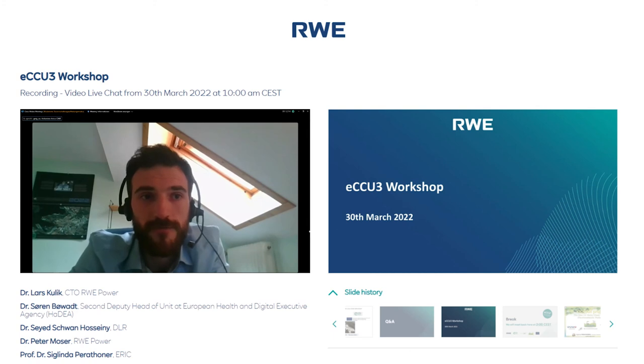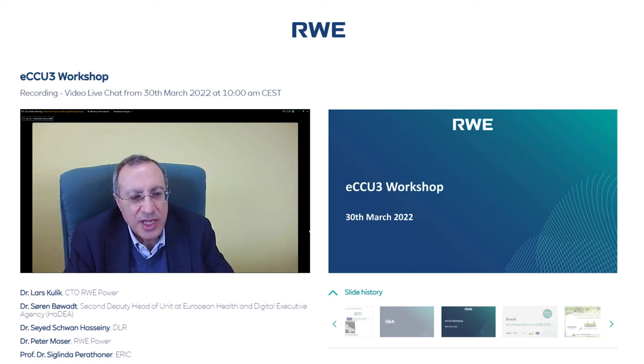Can I add a comment from my side? Sure. I think we also need to stabilize the oxidation state of the copper. The cuprite is a 1+ oxidation state. We have made in the LOTER.CO2M project some attempts using zinc to stabilize the copper oxidation state. And zinc copper oxide is well known for the methanol synthesis process. However, the productivity of carbon dioxide has not increased. So, of course, we need to stabilize the morphology. We also need to stabilize the electronic structure of the cathode catalyst.